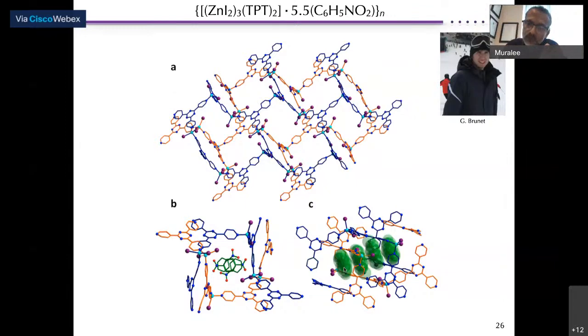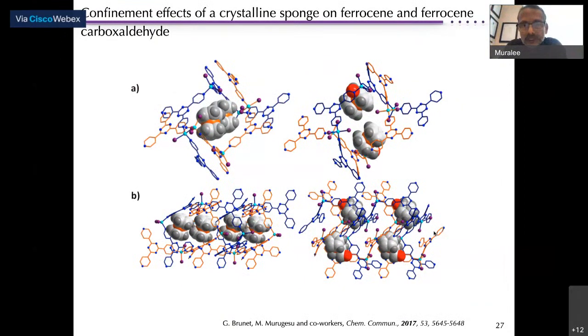They pack in a beautiful arrangement to form this electron density here, you can see, which can be removed to accommodate new guests. So can we do that? What we were able to do is to confine ferrocene and ferrocene aldehyde within this framework by simply taking the zinc framework and soaking it into a solution containing ferrocene.